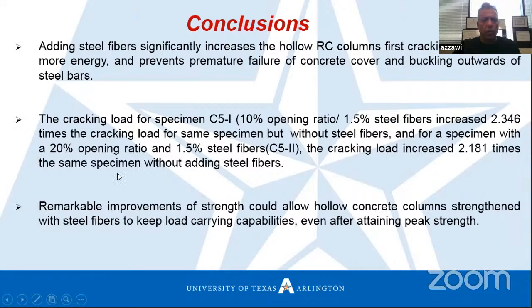Also, regarding the cracking load of specimens, I noticed from my research that the cracking load for specimen C51, meaning 10% opening with 1.5% steel fiber, increased around 2.4 times compared to the same specimen without the steel fiber. And for a specimen with 20% opening ratio and 1.5% steel fiber, the cracking load increased around 2 times compared to the same specimen without any fiber.